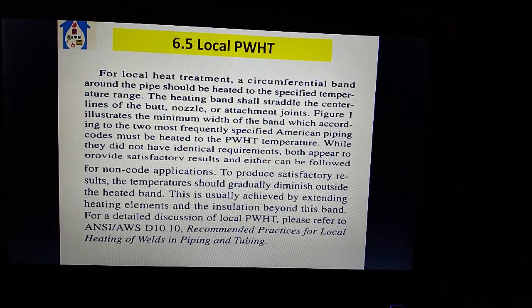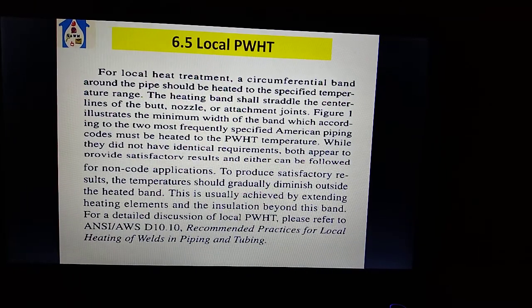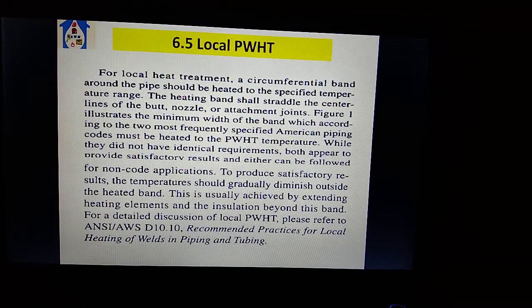Figure 1 illustrates the minimum width of the band which, according to the two most used requirements specified in American piping codes, must be heated to the PWHT temperature. While they do not have identical requirements, both appear to provide satisfactory results and either can be followed for non-code applications. To produce satisfactory results, the temperature should gradually diminish outside the heated band.